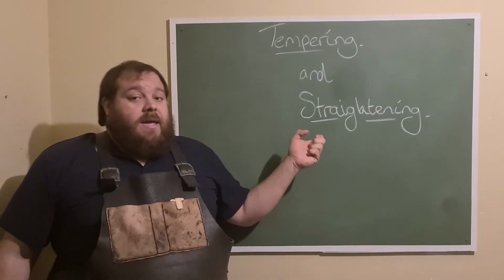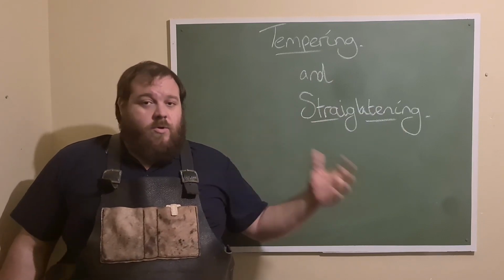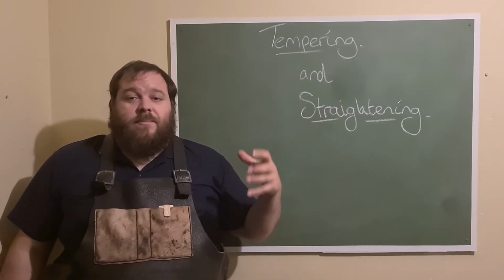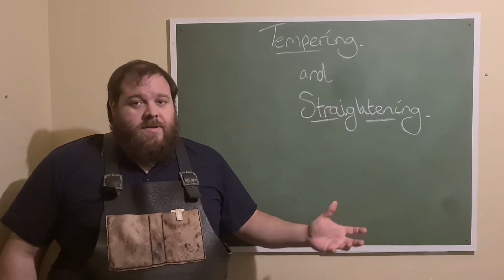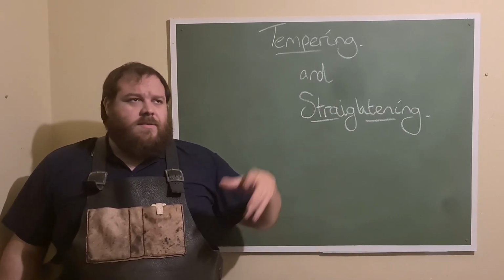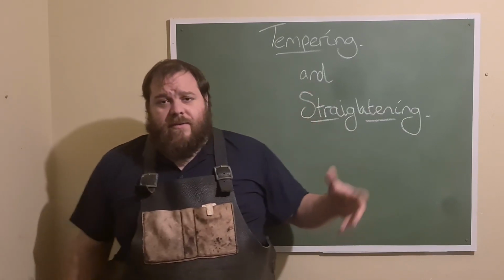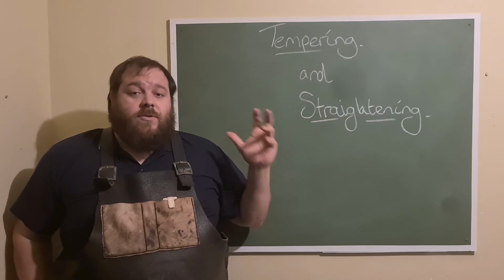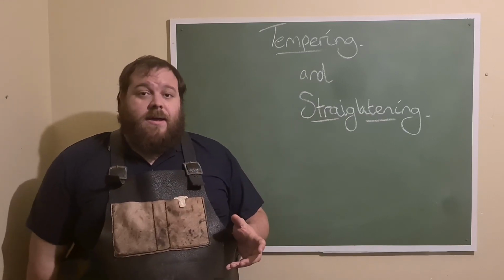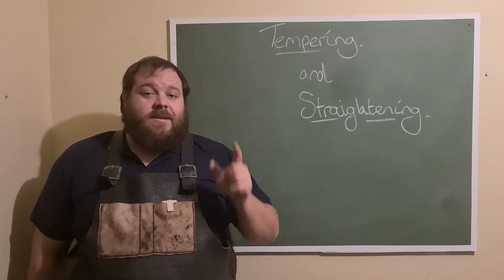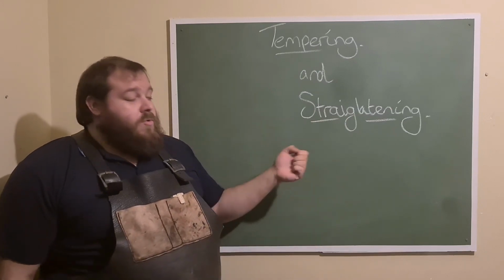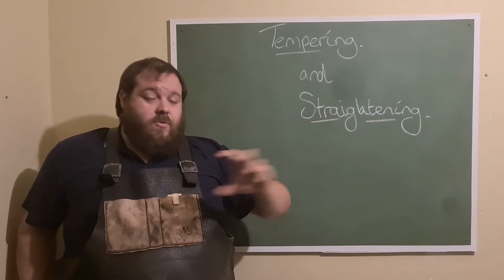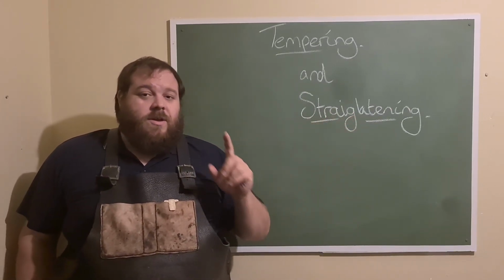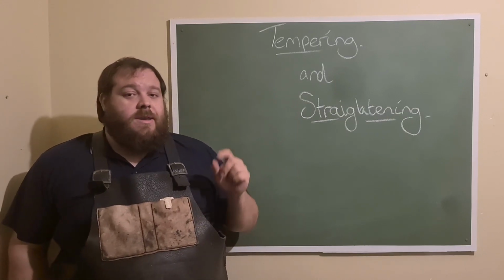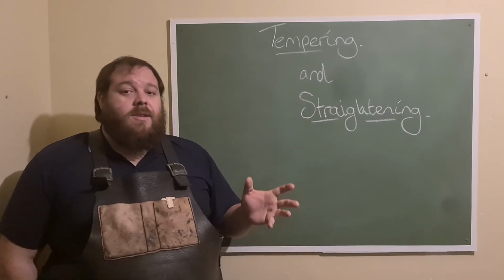Now, in our case, we can temper as we normally would with any other blade. You can temper it in the oven, 200 degrees Celsius, 180 degrees Celsius, whatever that is in Fahrenheit, 350, 400 Fahrenheit for 2 hours, like you would any other time. The difference is in straightening. Because you don't have a hardened piece, once you've done your first temper cycle, you no longer need to use shimmed tempering or anything like that.